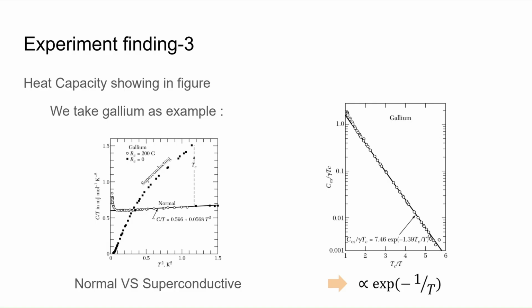But for the temperature close to 1.2, or C over T equals 1.4, it will abruptly drop to the normal state. And the right hand side proves that C over gamma T is proportional to exponential minus 1 over T. That means it is proportional to the exponential of minus 1 over temperature.